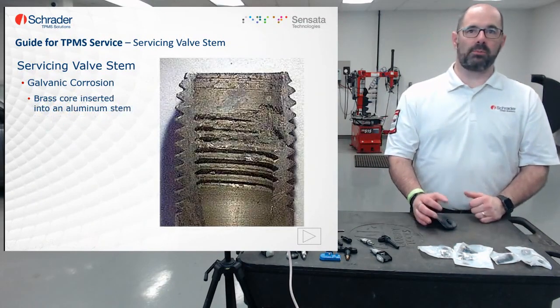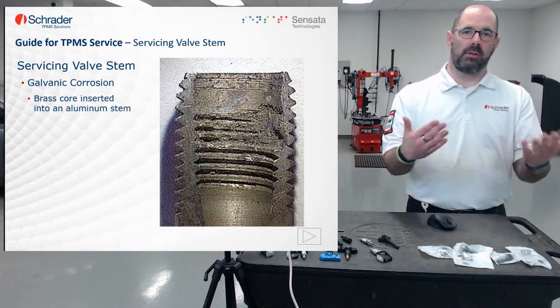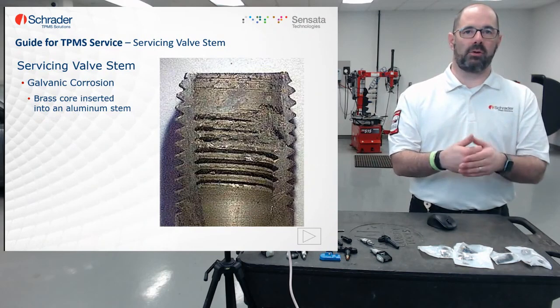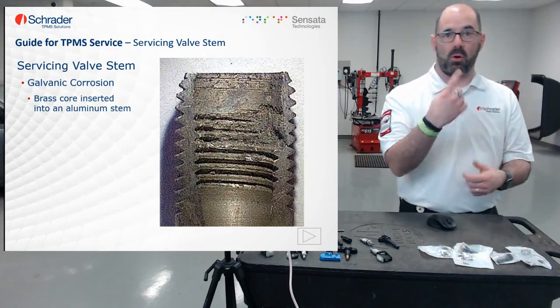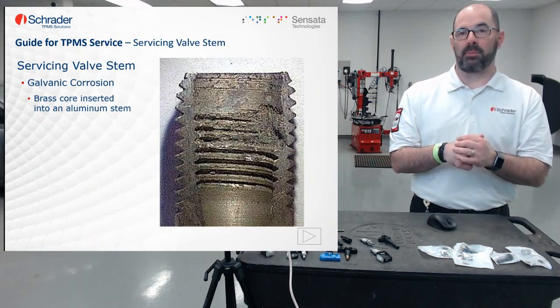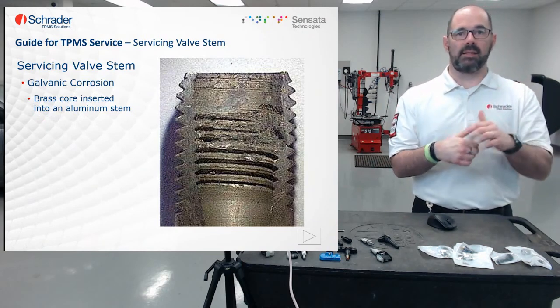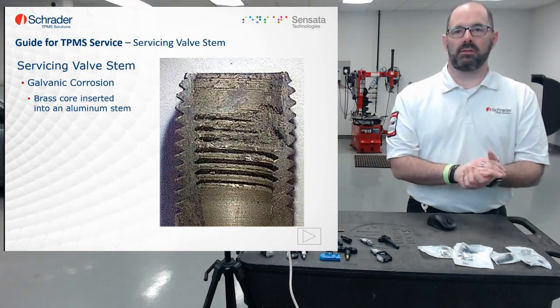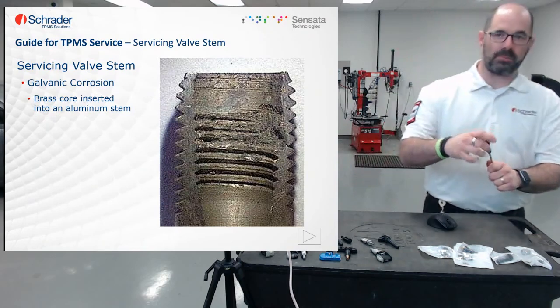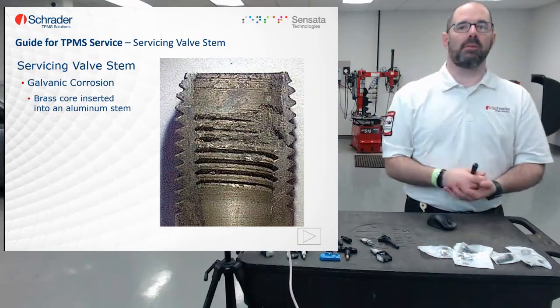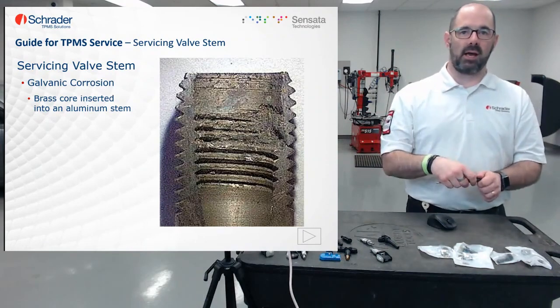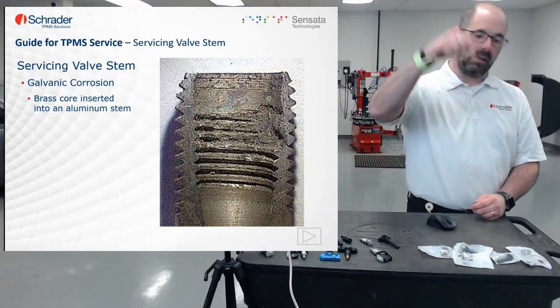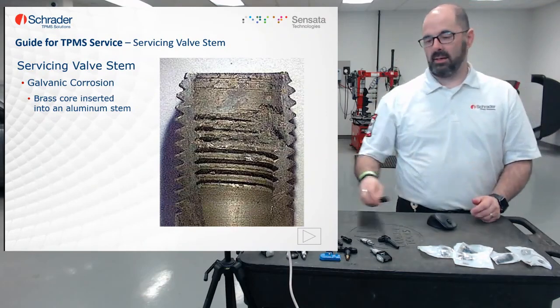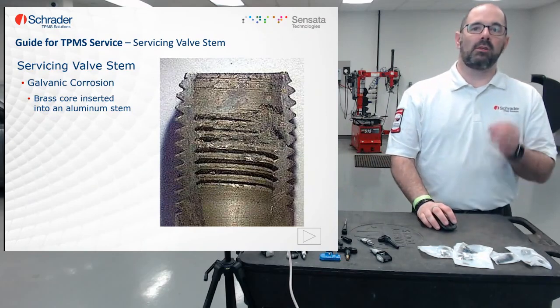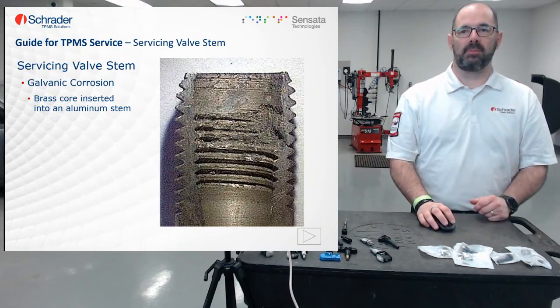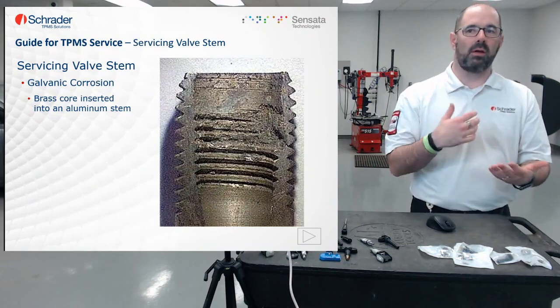But here's another one for you. Galvanic corrosion, as I said, is 2 dissimilar metals in contact. Chrome-plated cap on the aluminum valve, or what if this one, imagine if you put a brass valve core inside the aluminum stem. And we see that all the time. A technician will remove the valve core and just put it on top of the tire machine. When it's time to put the air back in the tire, they'll just reach out and grab the first thing they can get and put that inside. It's a common mistake that technicians make when servicing TPMS. Using a brass valve core inside an aluminum stem is another perfect combination for galvanic corrosion.